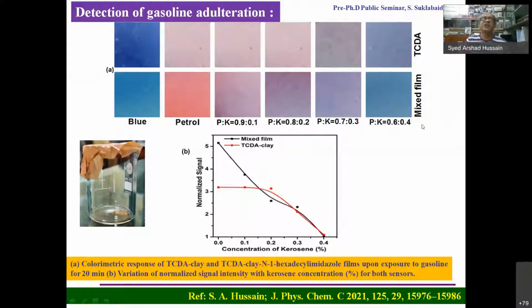You can see here the ratio, and then again we expose our blue phase film to this adulterated petrol, and here you can see the extent of polymerization is less. That means the presence of kerosene affected the phase change from blue to red. With increase in kerosene concentration, the extent decreases, and beyond this concentration, polymerization is not possible. So it can give an idea whether our petrol is contaminated with kerosene also.